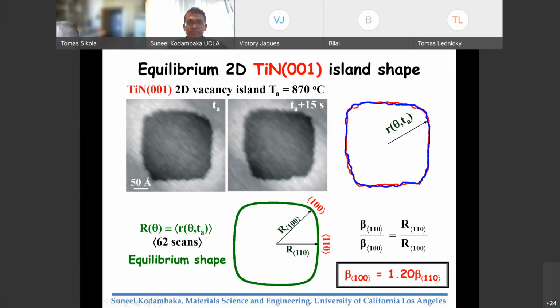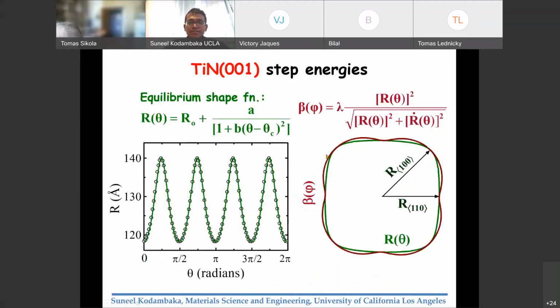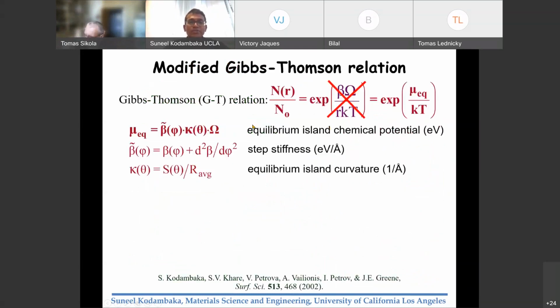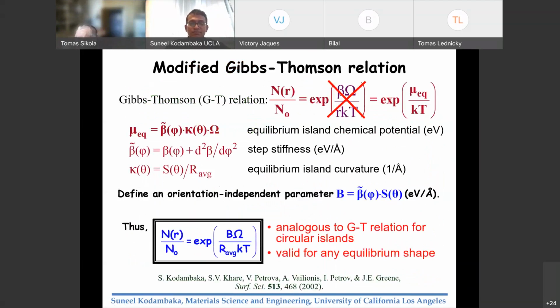Okay. Now, again, as I mentioned before, this is just the relative information, but now we can get the relative change in the step energies, and this is the polar plot, by doing this transformation. And once we have that information, now we need to get the step energy parameter. And to this, we use the island decay behavior. And I'll not go through the details here again, but I'll give you the gist. And that is that from island decay behavior, we get this parameter B, which is actually the step stiffness times the shape function, which is essentially the curvature times the average radius. So all this information is available, the shape function and the step energies parameter, from the island decay measurements.